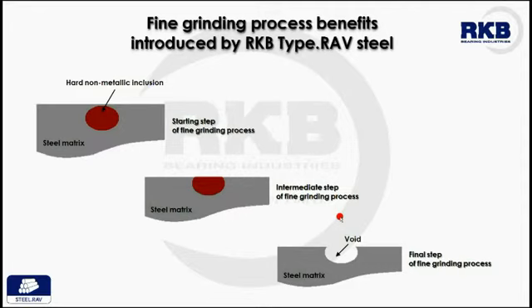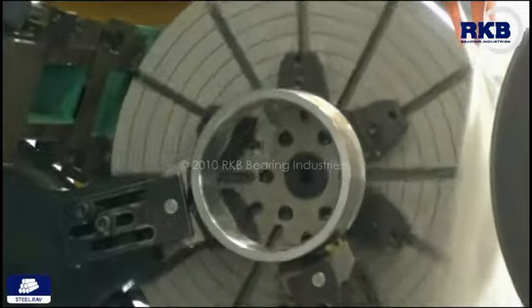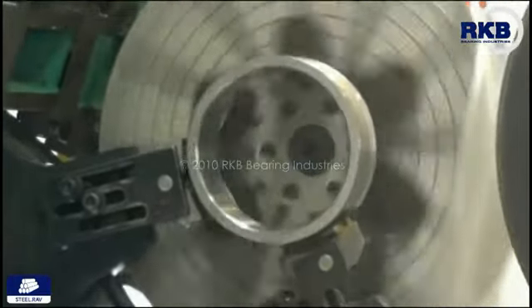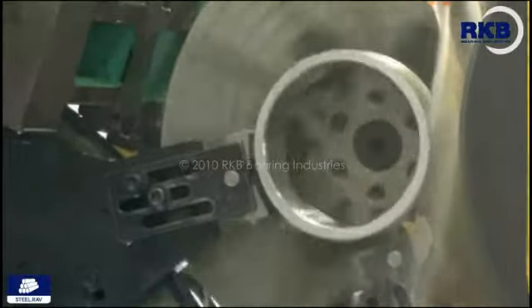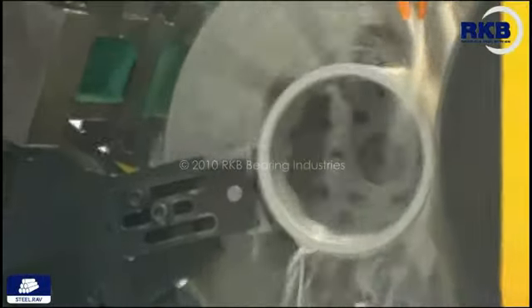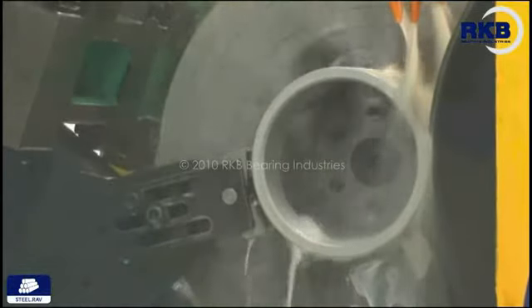Moreover, if the fine grinding process is carried out incorrectly, for example without an adequate cooling system, there is a high risk of metallurgical transformations in the material structure, which can lead to quality loss of mechanical properties, particularly in the ribs, where the surfaces are small and cannot dissipate the heat generated in this phase. As this movie clearly shows, RKB performs the fine grinding process in a proper manner. In this way, we avoid temperature rising during the manufacturing process, eliminating the possibility of metallurgical transformations in the material structure.